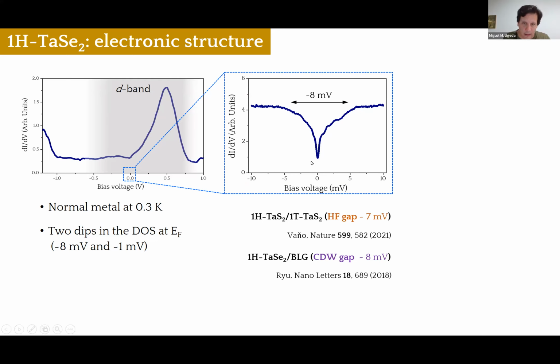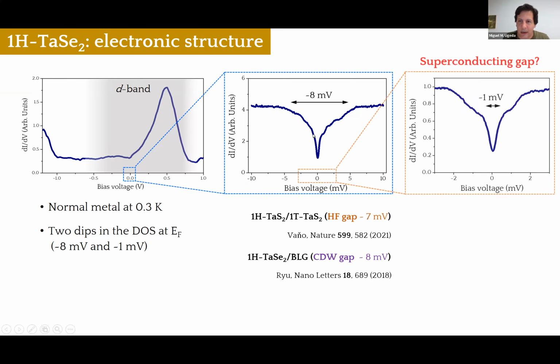For example, it's been attributed to a heavy fermion gap, also a charge density wave gap in this material. So it's not clear exactly what the origin of this dip is. I would say personally that it's a charge density wave gap, but I don't have smoking gun evidence about it. But what is interesting is that inside this dip, there is another one, a clear additional dip with a width of 1 milli-electron volt. That could be a superconducting gap. Okay, at least it's compatible with, not a hard gap, but it could be a superconducting gap.